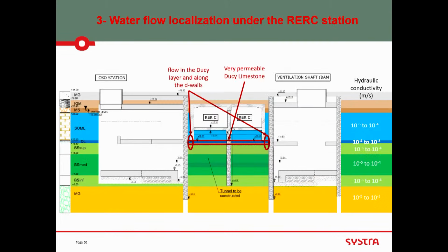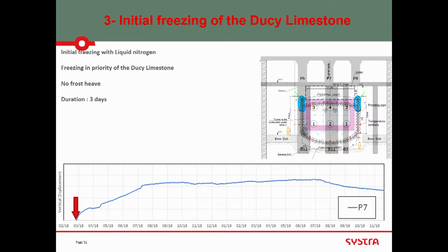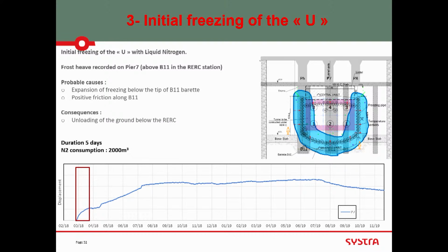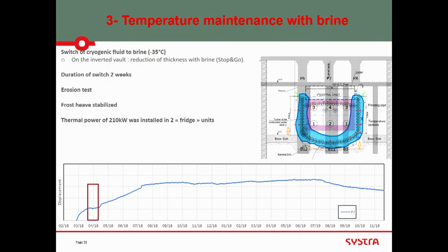So what we did, we sequenced, and the water was flowing into this layer, which is highly permeable. So we started freezing the soil by freezing only this layer. And then when this layer, which was highly pervious, was frozen, then we froze the remaining part of the soil, which was less pervious. And now, I won't go into detail, but you can see when it's blue, it's what we do. So the first step, we go with liquid nitrogen, duration 3 days. We start with the highly permeable layer. When it's done, we freeze the full U. You can see that there is some upward movement at this location, P7. We stabilize